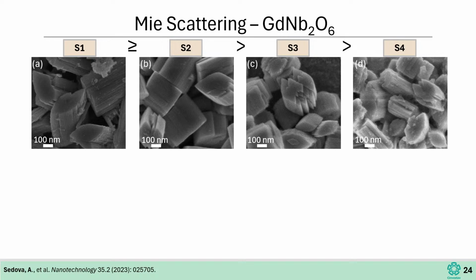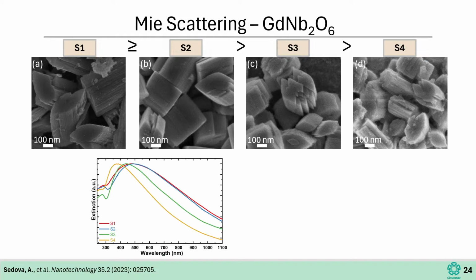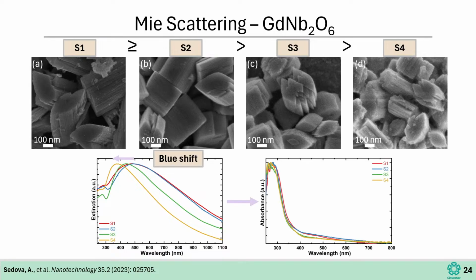So we synthesized particles with different sizes, where system 1 is the biggest particles and system 4 the smallest ones. We measured the extinction spectra and we saw the Mie scattering peak is blue shifted to the lower wavelengths. So how do we know that it's the Mie scattering peak and not other phenomena? We measure absolute absorbance, and for absolute absorbance, the scattering peak disappears.